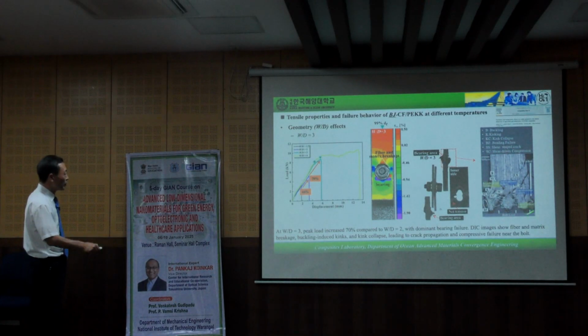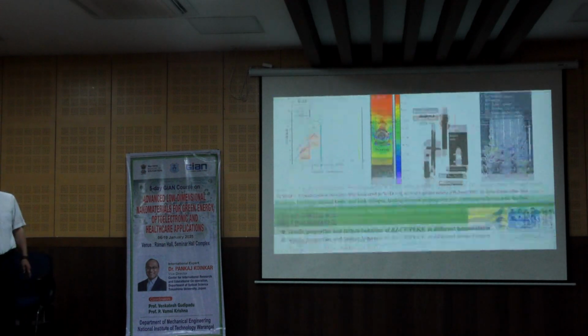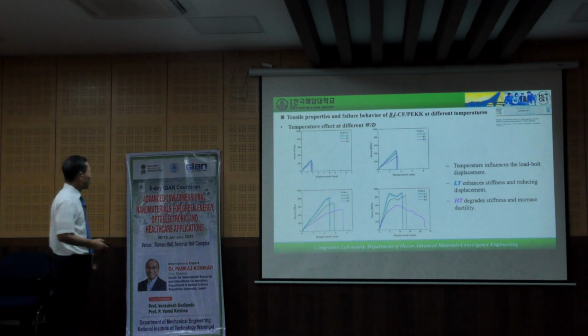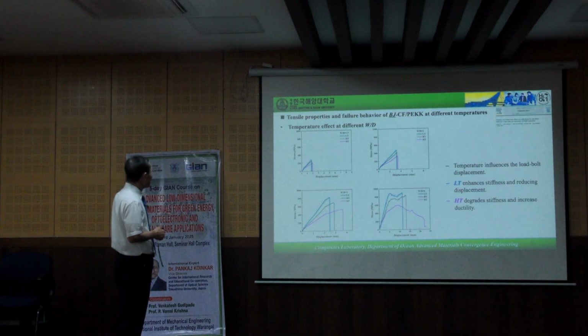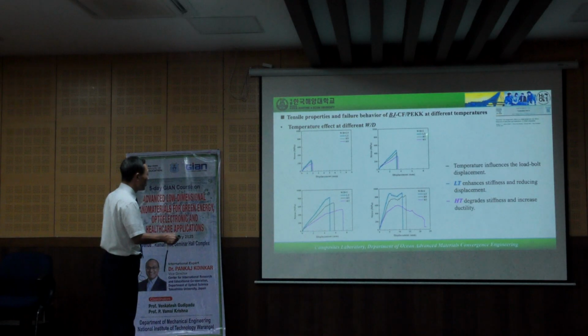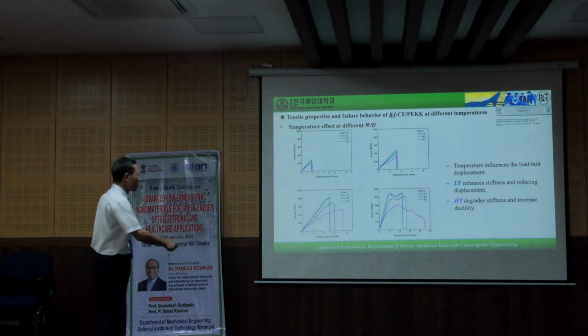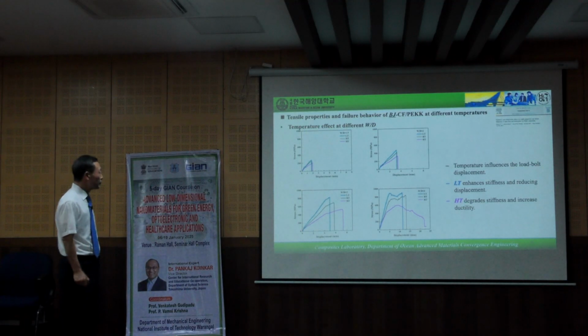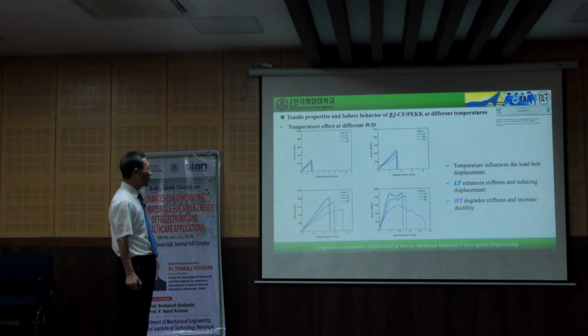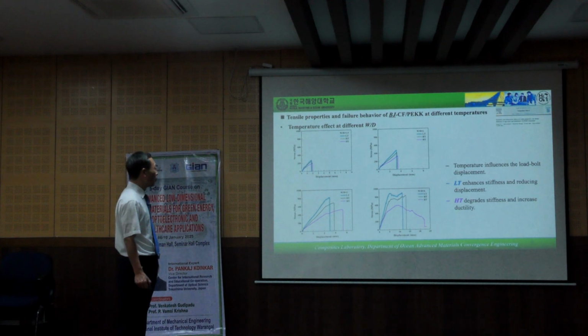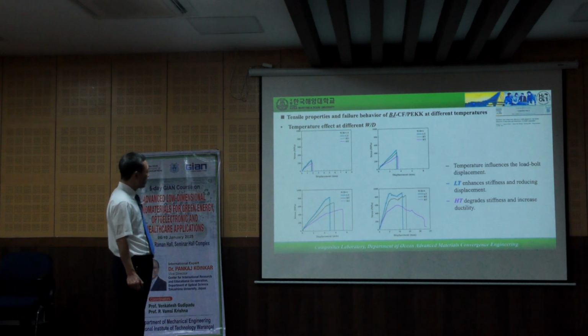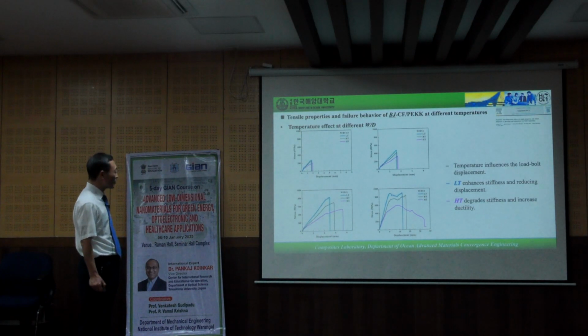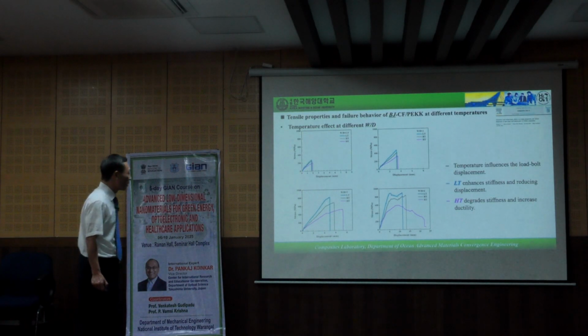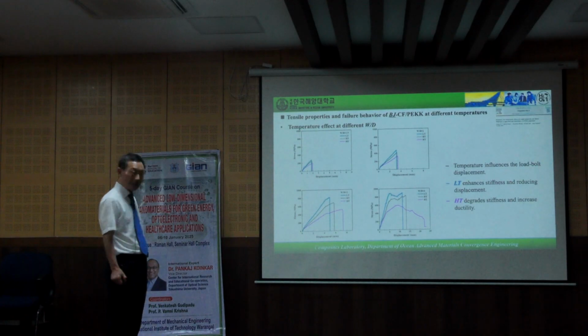Here, the fracture morphology. I'd like to change the temperature effect at the different W by D ratio, 1.5, 2, 3, 4. Just compare the result. Temperature influences the load bolt displacement. Low temperature enhances the stiffness and reduces displacement. High temperature degrades stiffness and increases ductility.